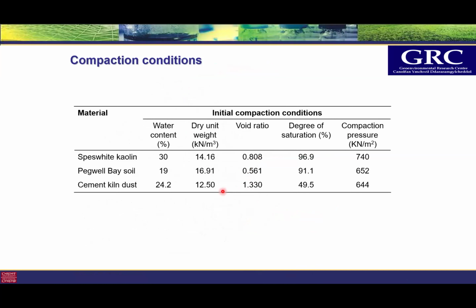Thank you. Yeah, sure. Here are the compaction conditions of the materials tested. You can see the initial water content, dry unit weight, and the degree of saturation. For Speswhite kaolin and Pegwell Bay soil the degree of saturation was more than 90%, whereas for cement kiln dust it is about 50%. As you know, cement kiln dust contains a lot of chemicals, and particularly calcium hydroxide, which is going to get formed when it comes in contact with water. These are the compaction pressures which are shown there.